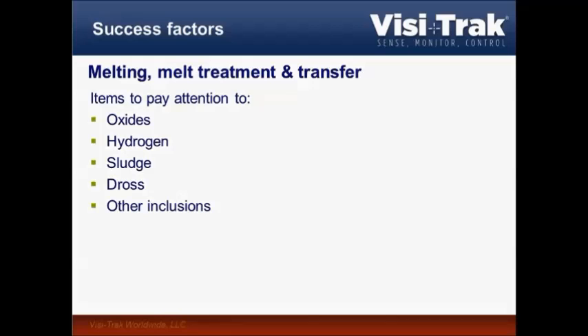Now, if we start looking at melting, melt treatment, and transfer, what we want to pay attention to is oxides. Any aluminum, especially when it's liquid, will build an oxide film very quickly on the surface, and that is fine as long as we don't fold the oxide layer into our part. So this is something we have to avoid. Hydrogen, as I said, hydrogen is the only gas that's soluble in liquid aluminum, but will then bubble out as soon as the metal freezes.